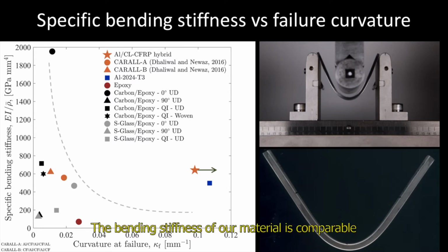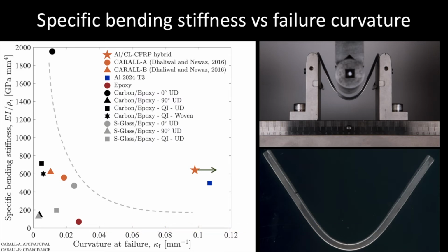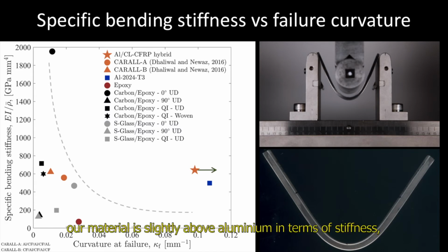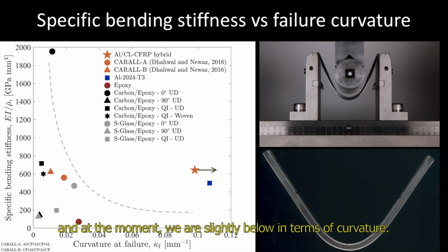The bending stiffness of our material is comparable to the stiffness of other aluminium CFRP hybrids and quasi-isotropic CFRP laminates, but we reach curvatures that are significantly larger than any of those materials. And compared with aluminium, our material is slightly above aluminium in terms of stiffness, and at the moment we're slightly below in terms of curvature.